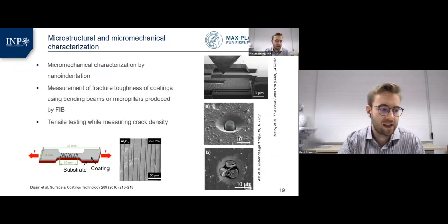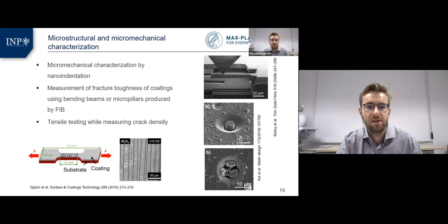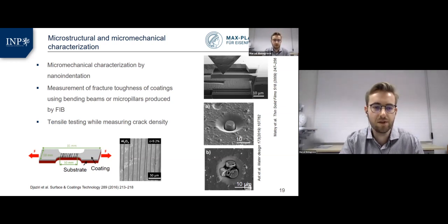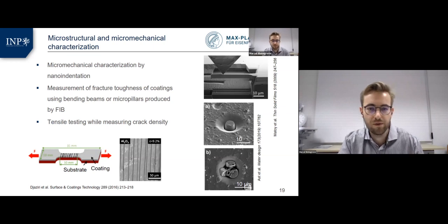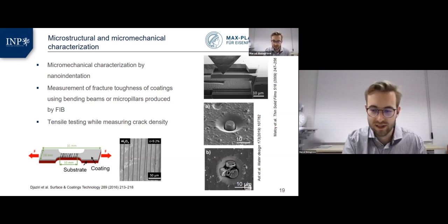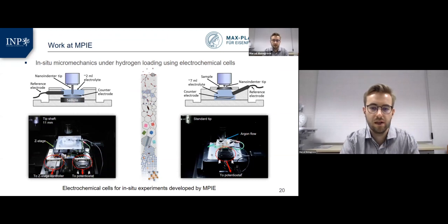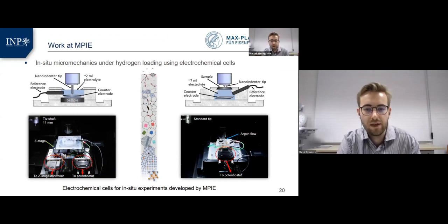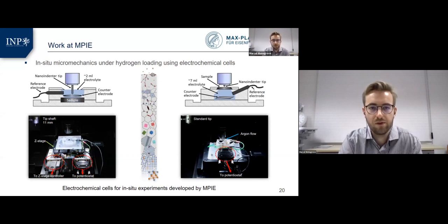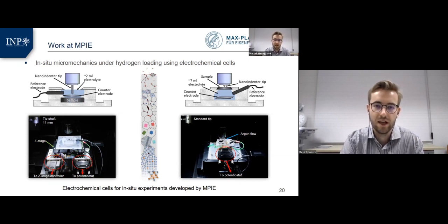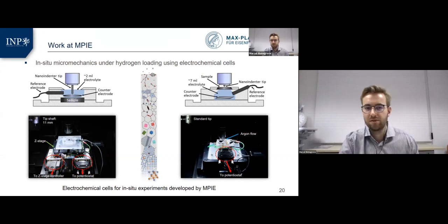Another important part is the micromechanical characterization, beginning with nano indentation and also the measurement of the fracture toughness of the coatings using bending beams or micropillars produced by the focused ion beam method. And also tensile testing on coated substrates is performed, while in situ monitoring the cracks that appear during tensile testing and obtaining very important and valuable insights on the crack density. Also, the MPIE has developed an electrochemical setup that allows experiments for the micromechanical testing in situ while simultaneously loading samples with hydrogen by an electrochemical method.